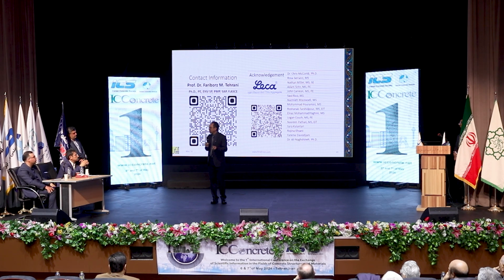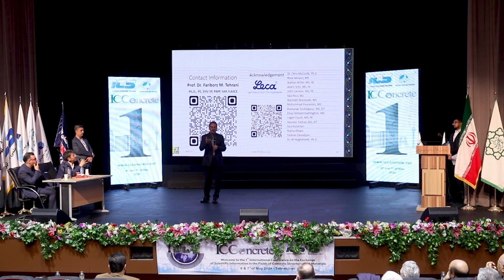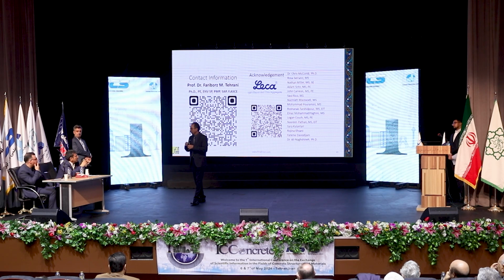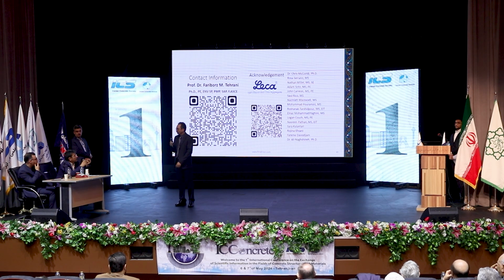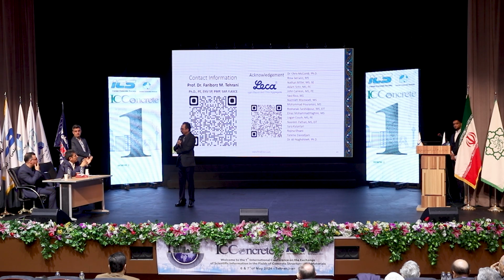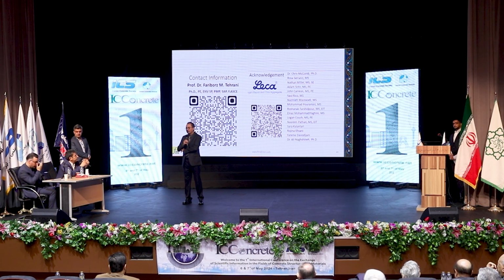Look at any foundation with 3,000 psi concrete that's placed every day, anywhere. They all crack. But is that a problem? Not exactly because of the autogenous shrinkage. Maybe we are talking about cracks that you cannot see. And how do we measure service life of concrete? If you measure the autogenous shrinkage and chemical shrinkage for high water cement ratio, it's not a lot. I mean, it's limited.